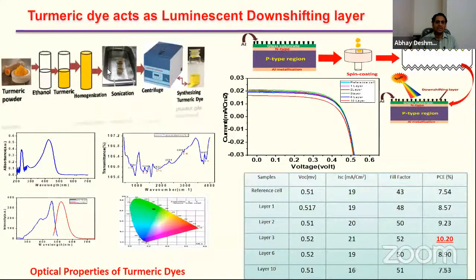And again, because people are trying with dyes, and as we know turmeric is a well-known dye which people use at home, and the cost is very low, right? Because every person is using it. Now if you take this turmeric and put it into ethanol, turmeric has a curcumin dye. Okay, and the solution you will see is yellow. This experiment you can do at home also. Take turmeric, put it in ethanol, and then just sonicate it. So curcumin dye will get separated from the turmeric, and the solution you will see is yellow. Put it under UV light, and then accordingly you will see a green light or something. So this is your absorption and emission. You see you have a 300 to 500 nanometer absorption, but emission is around the 550 nanometer range.